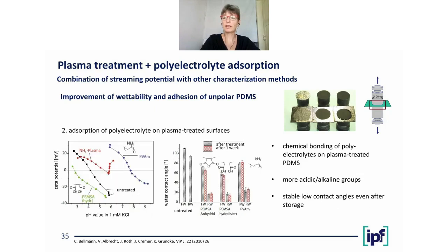But to overcome the problem with the recovery of the surface, we added an additional step. We adsorbed polyelectrolytes on these plasma-treated surfaces. And here again, you can see the effect of different polyelectrolytes: the polyacid that leads to a lower isoelectric point, an alkaline polyelectrolyte that leads to a higher isoelectric point. And the contact angle measurements on the right side show that with the adsorption of the polyelectrolytes, the effect on the contact angle and on the adhesion behavior was much longer stable than only after plasma treatment.